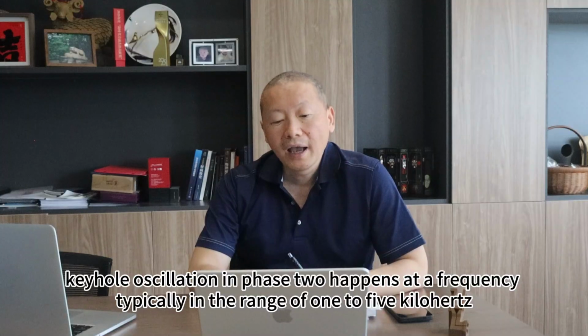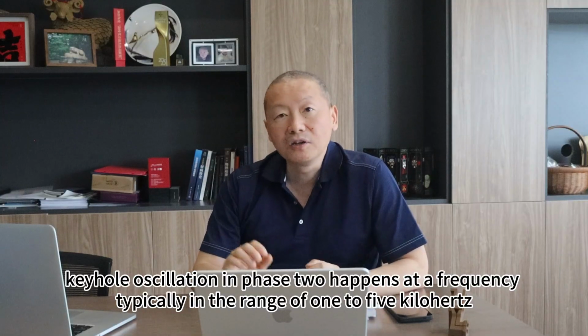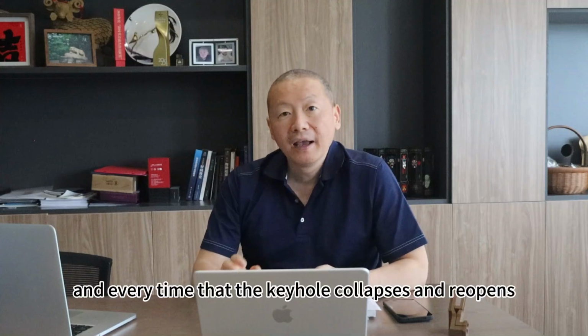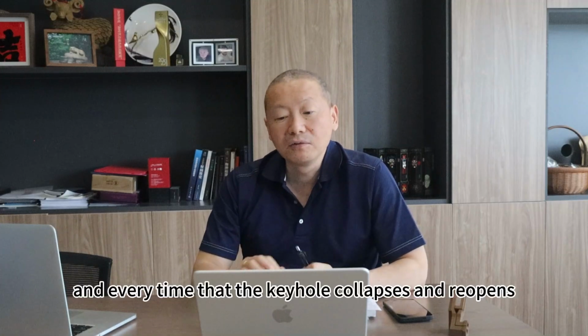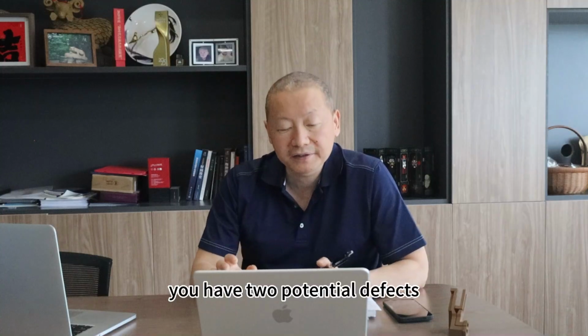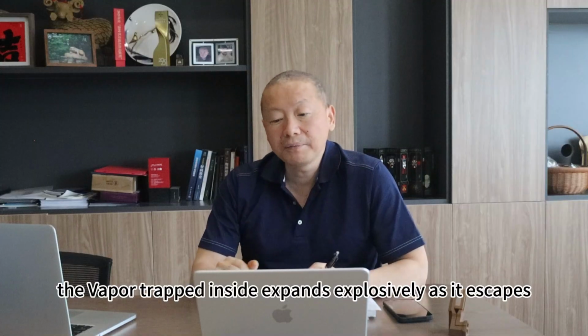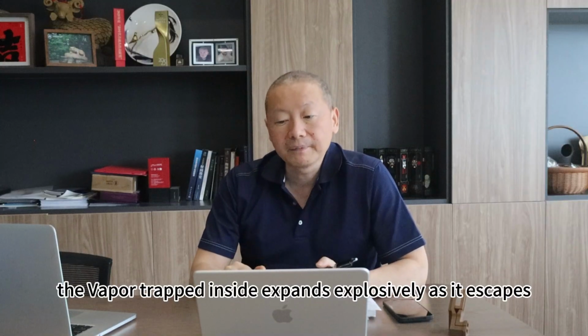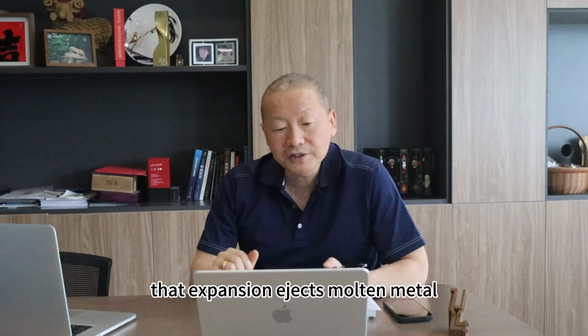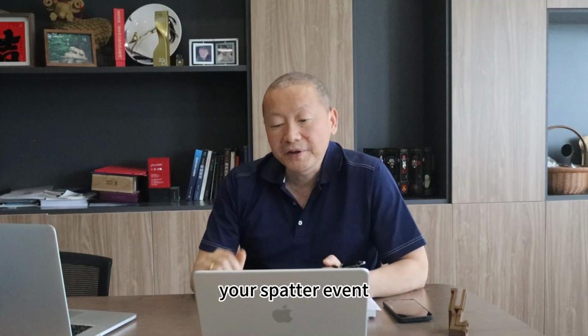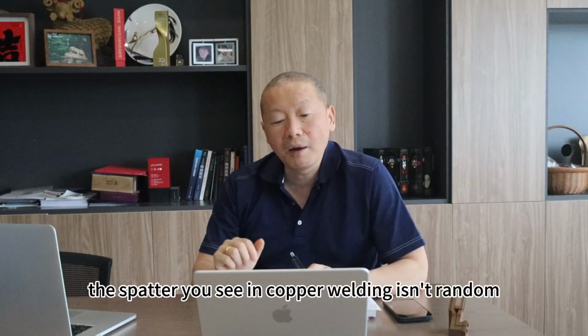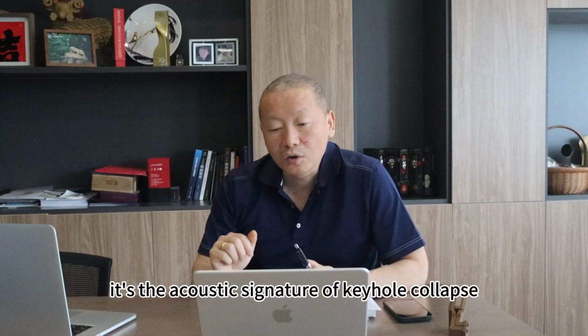It oscillates. Keyhole oscillation in phase 2 happens at a frequency typically in the range of 1 to 5 kilohertz. And every time that keyhole collapses and reopens, you have two potential defects. First, spatter. When the keyhole collapses, the vapor trapped inside expands explosively as it escapes. That expansion ejects molten material from the surface, and that's your spatter event. The spatter you see in copper welding isn't random. It's the acoustic signature of keyhole collapse.